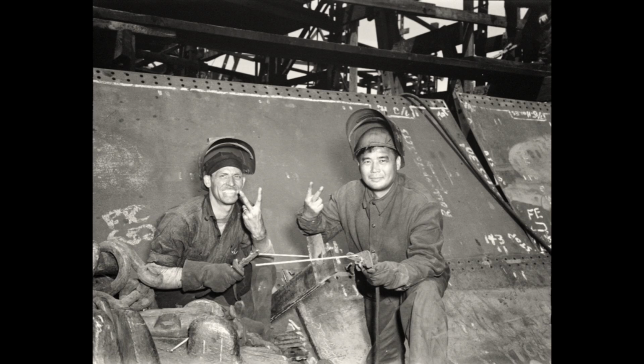This abbreviated training produced welders whose skills were narrowly focused but sufficient for the specific task. They learned to weld armor plate. Nothing more. It was enough. The quality control process relied on visual inspection and basic testing. Kowalski, or another experienced welder, examined each completed modification, looking for cracks, incomplete fusion, porosity, or other defects that would compromise strength. Welds that failed inspection were ground out and redone. Approximately 8% of initial welds required rework, a surprisingly low failure rate given the improvised conditions and abbreviated training.